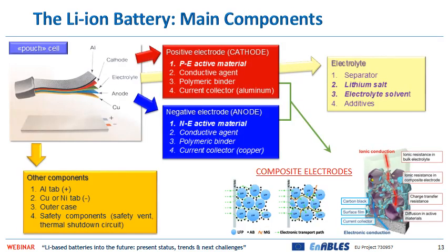Here you have a slide which summarizes the main components of a standard lithium-ion cell. Like any other battery, a rechargeable lithium-ion battery is made of one or more power-generating compartments called cells. Each cell has essentially three main components: the cathode, the anode, and the electrolyte. Electrodes are generally composite, including active materials, conducting additives, and binders, and are supported on metal current collectors made of aluminum for the cathode and copper for the anode.